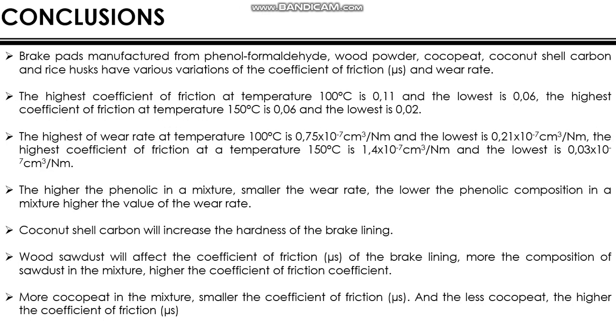Conclusion: brake pads manufactured from phenol formaldehyde, wood powder, cocopeat, coconut shell carbon, and rice husk have various variations of the coefficient of friction and wear rate. The highest coefficient of friction at temperature 100 degrees Celsius is 0.11 and the lowest is 0.06. The highest coefficient of friction at temperature 150 degrees Celsius is 0.06 and the lowest is 0.02.